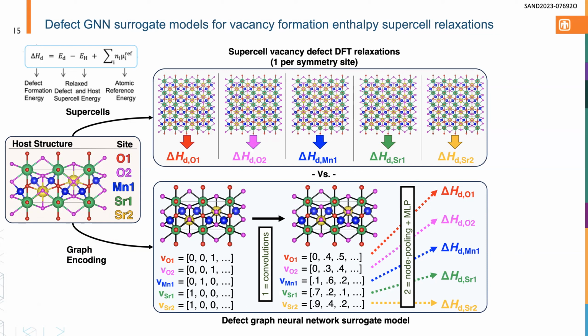see just a schematic of the feature vectors associated with each atom in that graph. And then you just perform convolutions. So we're not going to get too much into the math, but the point is that based on the bonds that you draw on the crystal structure and the geometry and the neighbors that you concatenate over, you can basically update those feature vectors for a particular atom through deep neural network layers.